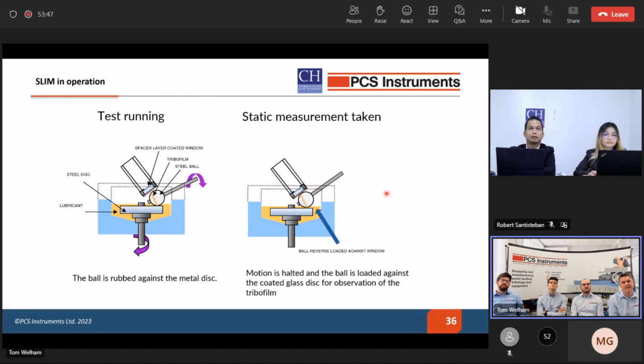So the way it works in the MTM, when we're running a test, the ball is rubbed against the metal disc, using a time step that allows us to build up the tribofilm. And then we backload the ball against this glass window that sits above the lid of the MTM. This is with the ball stationary. Then we take a picture using an attached camera, and that allows us to translate the image into a measure of film thickness or tribofilm thickness.